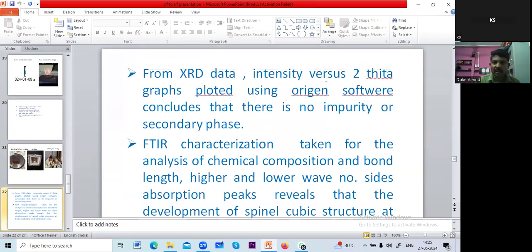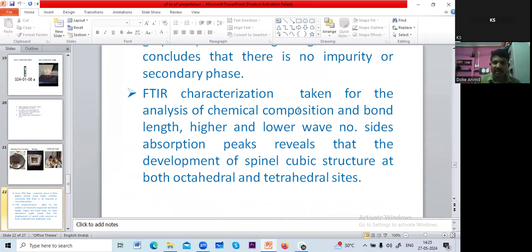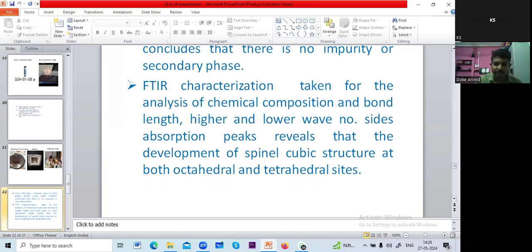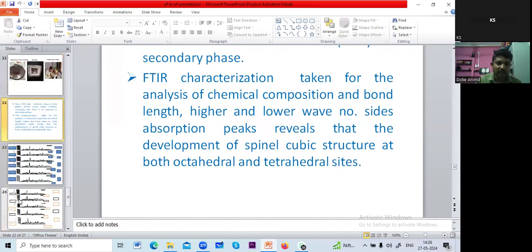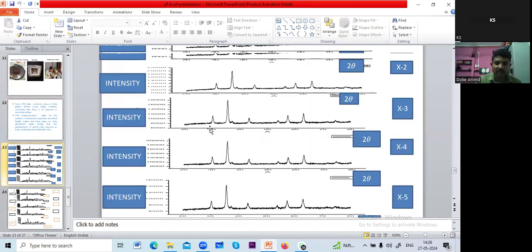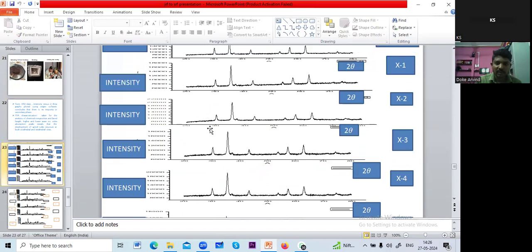From XRD data, the intensity versus 2 theta graph plotted using Origin software concludes that there is no impurity or secondary phase. The FTIR characterization was taken for the analysis of chemical composition and bond length. Higher and lower wave number side absorption peaks reveal the development of spinel cubic structure at both octahedral and tetrahedral sites. The graph of this characterization is mentioned in this slide. That is the XRD intensity versus 2 theta graph.